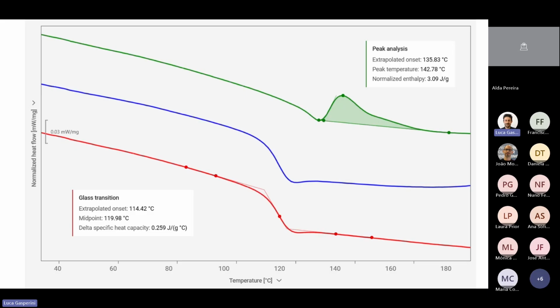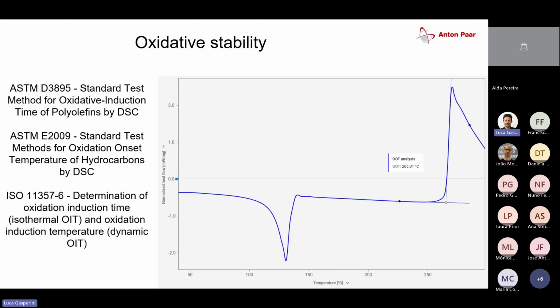So the DSC is also a tool how we can monitor the curing reactions and say if the curing was sufficient enough for the application that we need. Florian has mentioned wind turbine blades. So this is something where DSC is also being used as a quality control tool to find if curing was sufficient. I've mentioned that if we take samples to higher temperatures under the influence of oxygen, we can also monitor oxidative stability, which can be done in a very simple way, but there is a list of international standards, either ASTM or ISO standards, that actually tell how this oxidation stability can be measured, monitored, what it means, and how it's supposed to be performed.